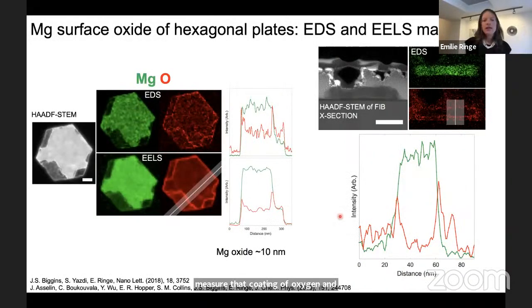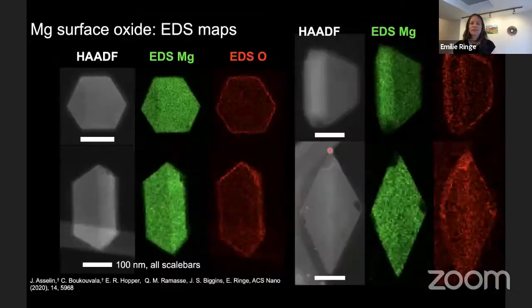And we can do a line scan through that. And well, it kind of depends on which particle you measure, to be completely honest. But roughly, you get a magnesium oxide of about 10 nanometer on a particle that's 40, 50 nanometer of magnesium metal thick.